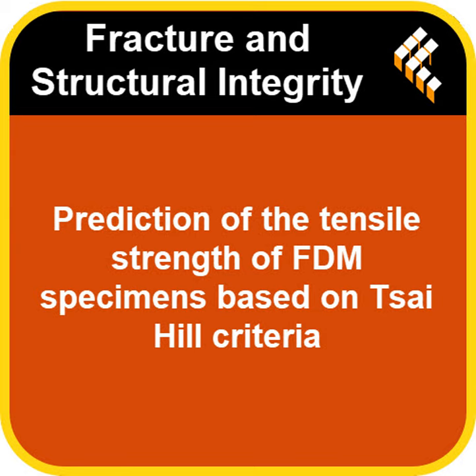Oh, definitely. Really different results depending on that raster orientation. All right, let's hear it. What happened in the tug-of-war? Which grain held up best? Well, no huge surprise maybe, but when the internal lines, the filaments, were running straight along the direction they were pulling, that 0 degree orientation, yeah, those parts had the highest overall tensile strength. They could take the most pulling force. Okay, strongest along the grain. Yeah. Did the contour, that outer shell, help there? Interestingly, for that 0 degree pull, adding the contour didn't make a huge difference in the maximum force they could withstand.